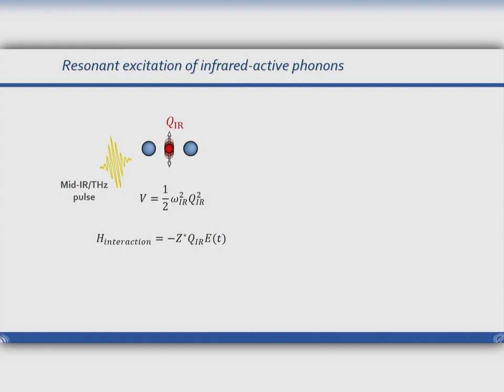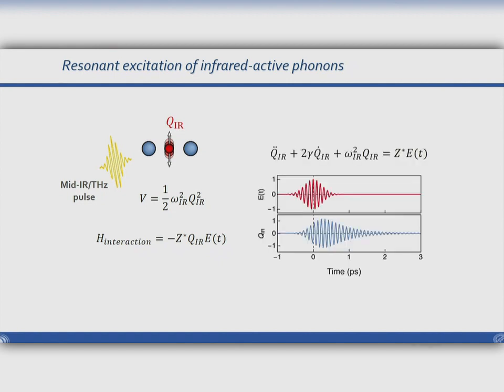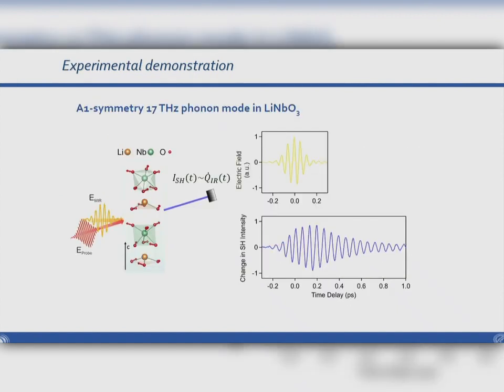of this atomic coordinate. You can write down the equation of motion now, and if you now tune your excitation pulse into resonance with the frequency of this phonon, you can see that as long as the pulse is present, you enhance the amplitude of this mode, and then it decays back to its original position. So this is a perfect coherent excitation of this vibrational mode. And while this is theory, we can also measure this.